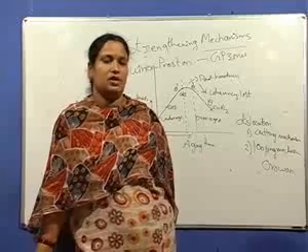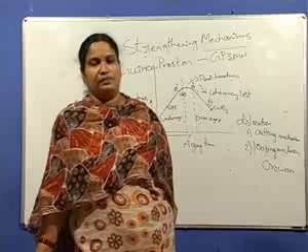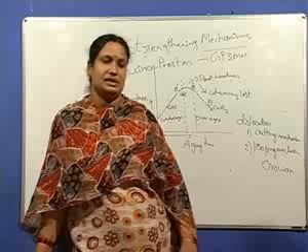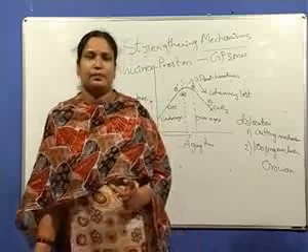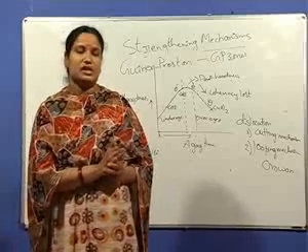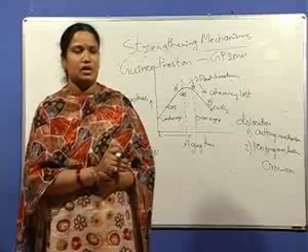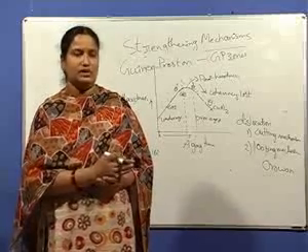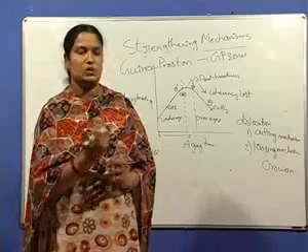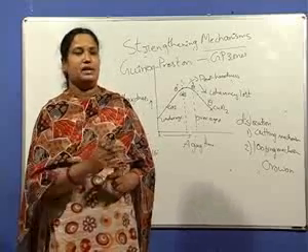The cutting mechanism operates when the precipitates are very fine and soft, so the dislocation can easily cut the precipitate particles. And the looping mechanism occurs when the precipitates are coarser, so the dislocation has to bend around the precipitate particles and then bypass them. Both these mechanisms require higher stress: bending of the dislocation around the precipitate particles, and cutting the precipitate particles.